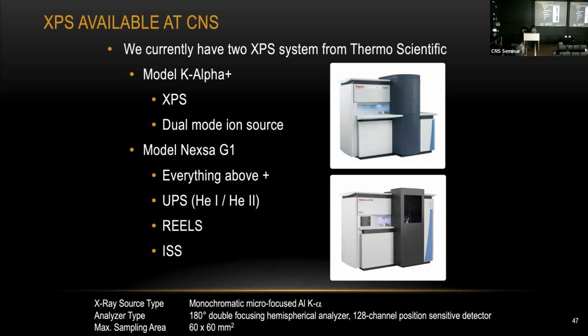So the whole idea of the UPS measurement is very similar to XPS. You are still knocking some photoelectrons out from the surface. But since we are using helium-1 and helium-2, their energy is much lower. Helium-1 is around 21.2 eV, and helium-2 is about 40.8 eV. So you can see, compared to the X-ray we use for XPS measurement, it is much, much lower. By using much lower energy, you are probing right on the top layer of your sample, and you are mostly only getting valence band electrons out from your surface.